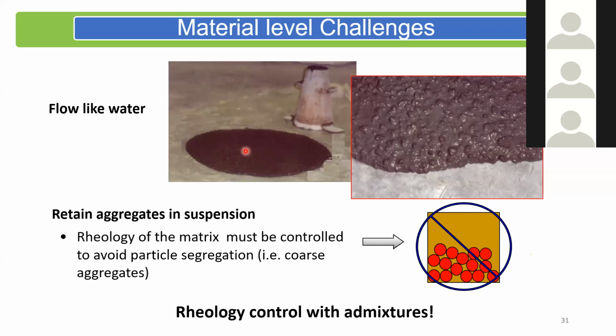But if I make it less viscous, then there is a tendency of segregation, because now the fluid phase in the material is less viscous. So there will be a chance for aggregate to separate out. So I need to get this very viscous material to flow under gravity-induced stress. It should be self-leveling while it carries the aggregate with it. This is the key requirement that we have for producing self-consolidating concrete.